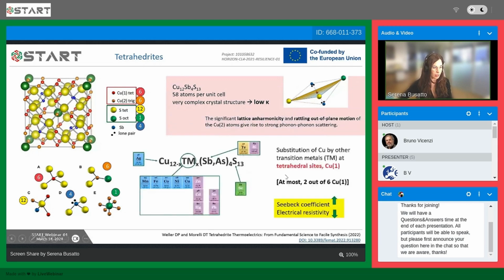Here you can see how all these different metals can be incorporated into the tetrahedral sites, the copper sites. So there are two different copper sites, tetrahedral and trigonal copper sites, and 2 out of the 6 tetrahedral copper sites can be substituted by other transition metals, conferring higher electrical conductivity and a higher Seebeck coefficient.